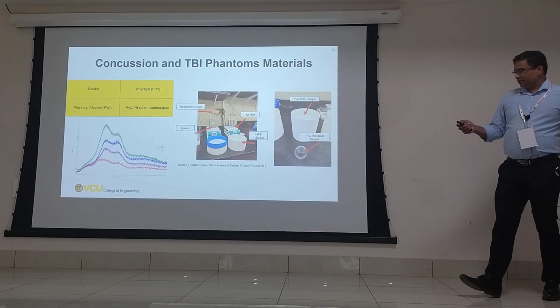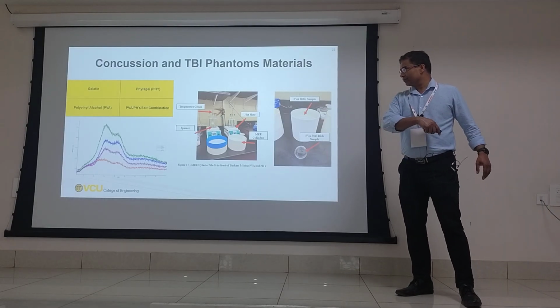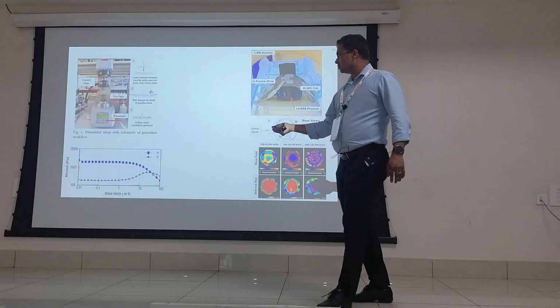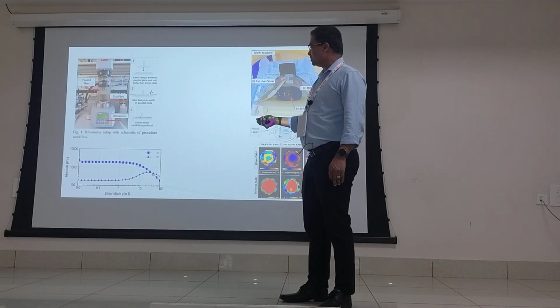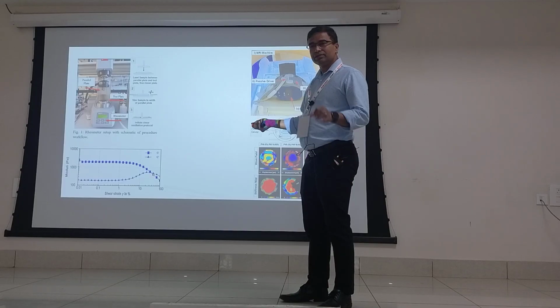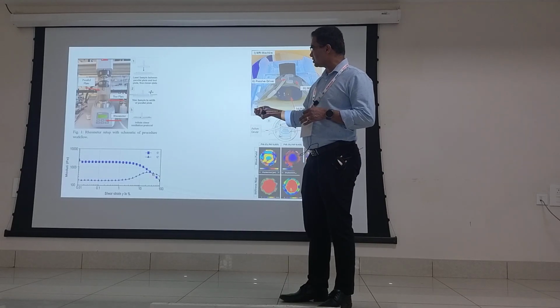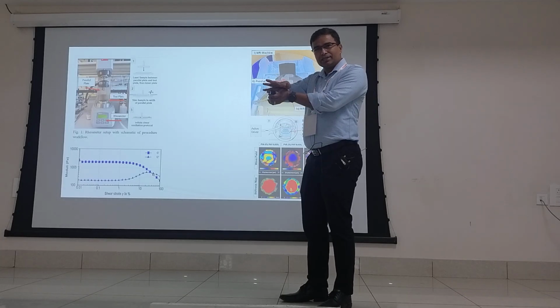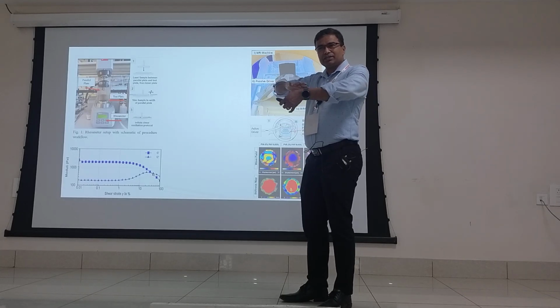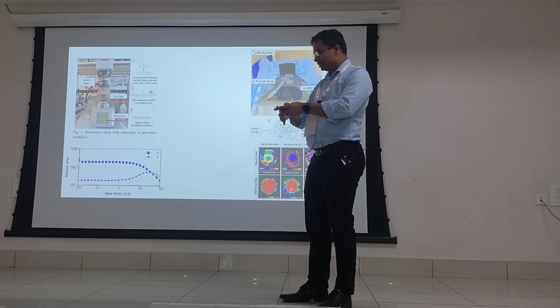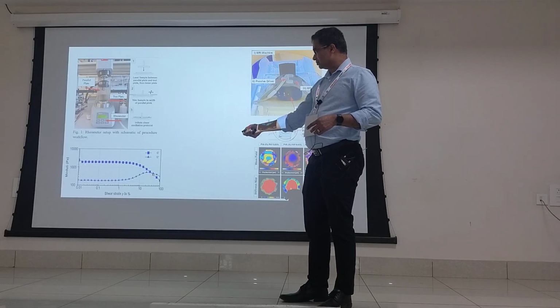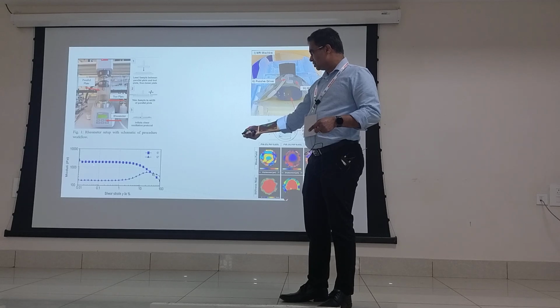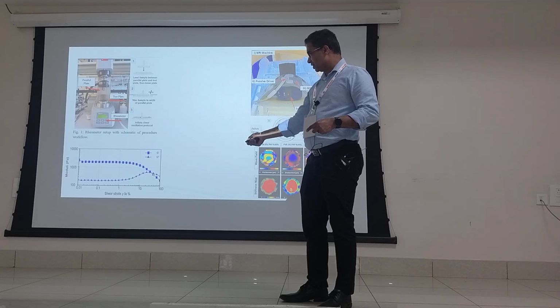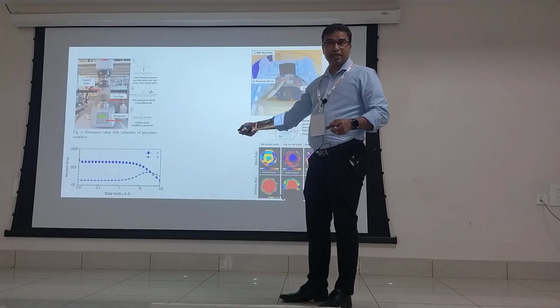A rheometer will give you G prime and G double prime. So we use a rheometer, but it takes certain size samples, so we have to create these samples. Basically, it shears and measures the elastic constant. It has different shear rates, and this is how it gives you a graph. Okay, this is your G prime, this is your G double prime, and this matches that of the brain.